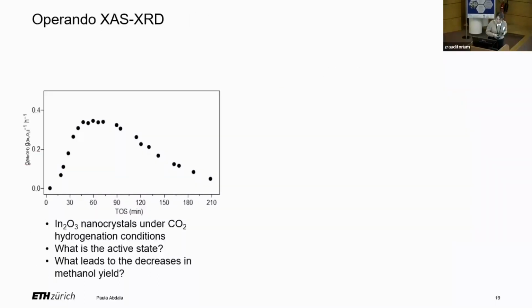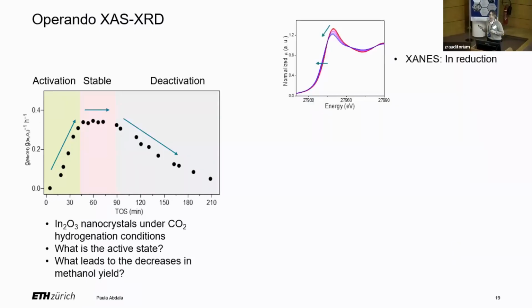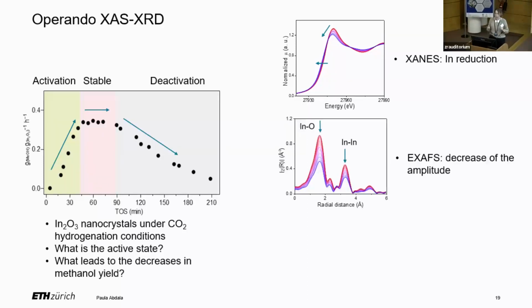So with this, we can first look at the performance at the outlet of the capillary. This is methanol produced per gram as a function of time on stream. Initially, we observe an activation and stabilization of the material, followed by a stable performance, which later on deactivates. Now, looking at the XANES data, it tells us that there is a reduction of the indium oxidation state with time on stream. Now, EXAFS data tell us that there is a change in local environment: the indium-oxygen and indium-indium spheres are decreasing in intensity. The magnitude of these spheres is decreasing.